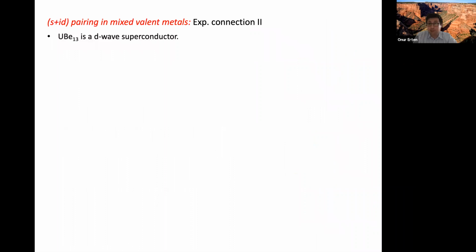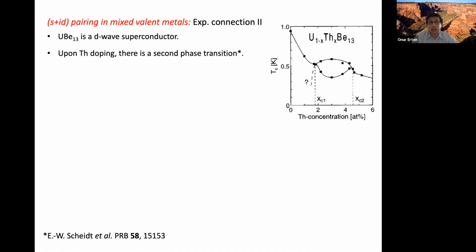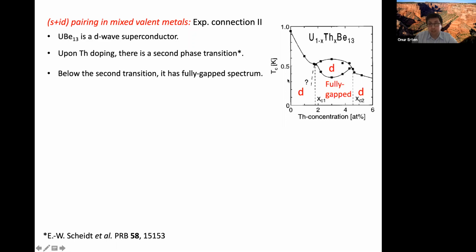All right, the second experimental connection. I've been telling you that this really sounds like a heavy fermion. So let's look at heavy fermions. Uranium beryllium 13 is a D-wave superconductor. This is well established from every experiment. And upon thorium doping, there's a second phase transition here. And it's been well established that below the second phase transition, it becomes fully gapped.